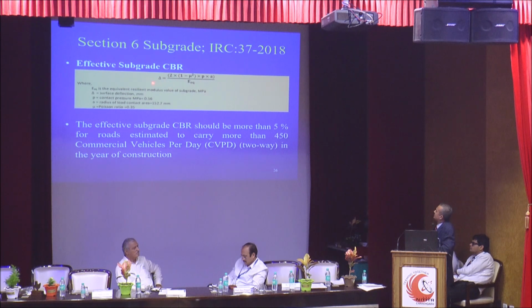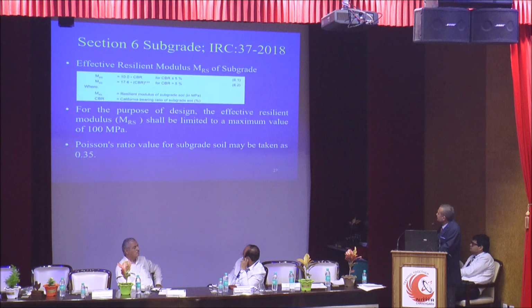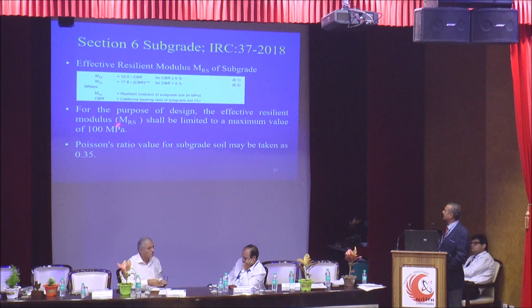Effective subgrade CBR, this is deflection. We calculate the surface deflection of the 2-layer system, and then we calculate E equivalent of the single layer. The effective subgrade CBR should be more than 5% for roads estimated to carry more than 450 commercial vehicles per day. This is the correlation which has been developed with dynamic conditions. For the purpose of design, the effective resilient modulus shall be limited to a maximum value of 100 MPa. In so many projects in Rajasthan, the designers have taken even 22%, 24%, 28% CBR. So they have exploited IRC 37 like anything. So now it has been restricted to 100 MPa. This is the Poisson ratio value.